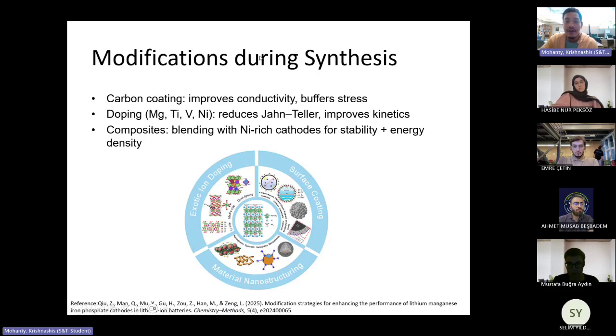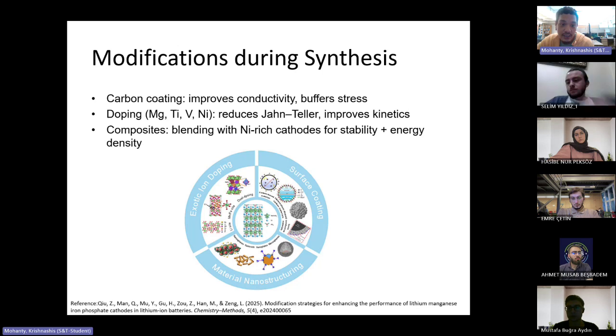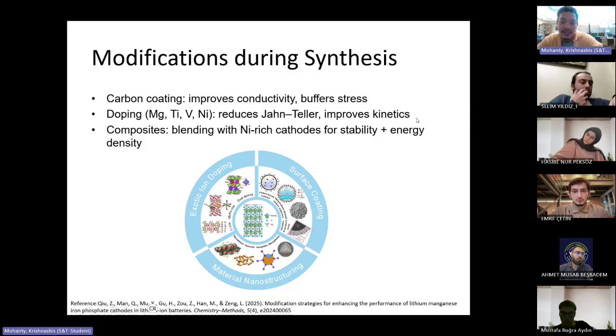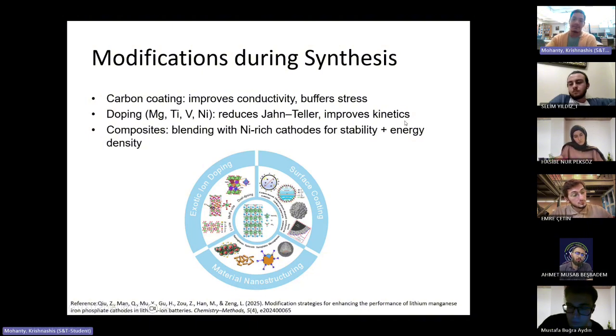And then again, after you have LMFP, because you understood adding manganese improves LFP structure, how about we add more ions into LMFP itself to make it better? By adding ions like magnesium, titanium, and nickel, people have observed they were able to reduce the Jahn-Teller effect, which again reduces capacity and energy fade. It also improves kinetics. So further research is being done by incorporating more foreign elements and stuff like that.